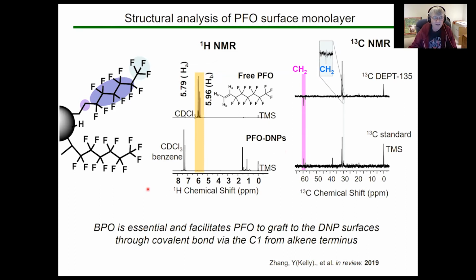Yet most of the time, we don't think about applying NMR to nanoparticles. For metal nanoparticles, there are too many electromagnetic interference effects, and lines broaden horribly and you really can't see anything. What we've discovered is that if you use nanodiamond, you can apply NMR to directly look at these molecular layers. So you can do fluorine NMR, proton NMR, and carbon-13 NMR.